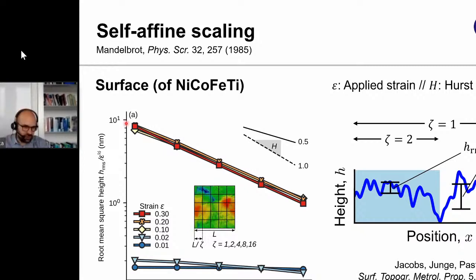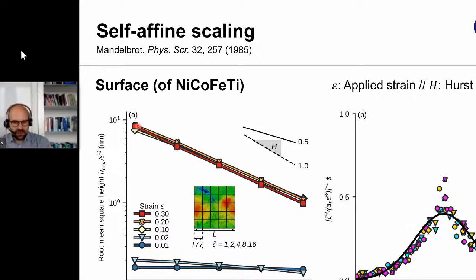And what we see is shown here: y-axis HRMS, x-axis magnification. Before yield, these are the blue curves down here. After yield, it jumps to a power law behavior of HRMS as a function of magnification, which indicates self-affine scaling of the surface topography. So we can actually do a little more detailed analysis.